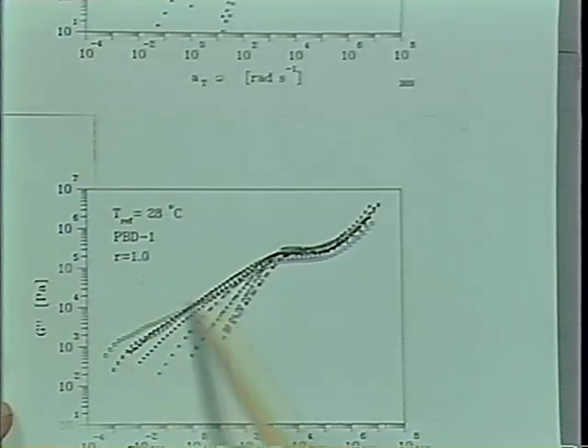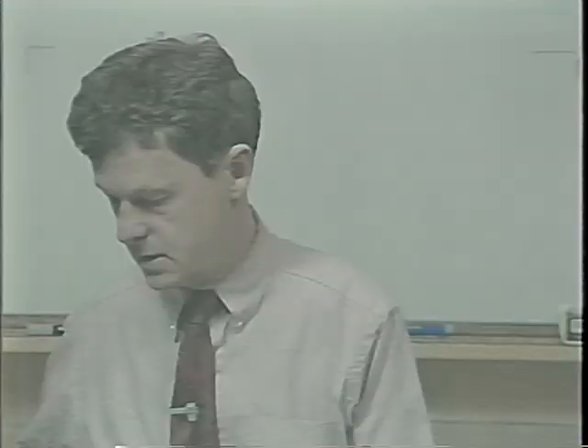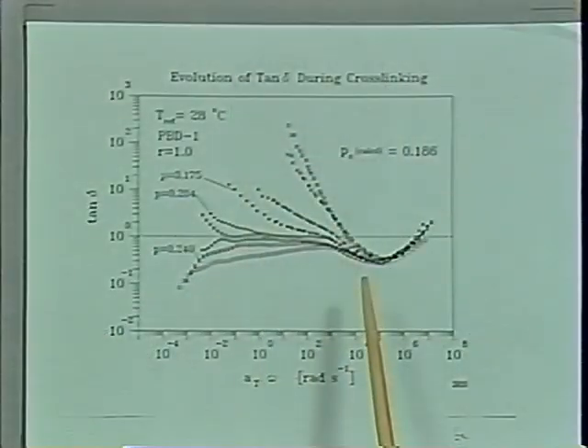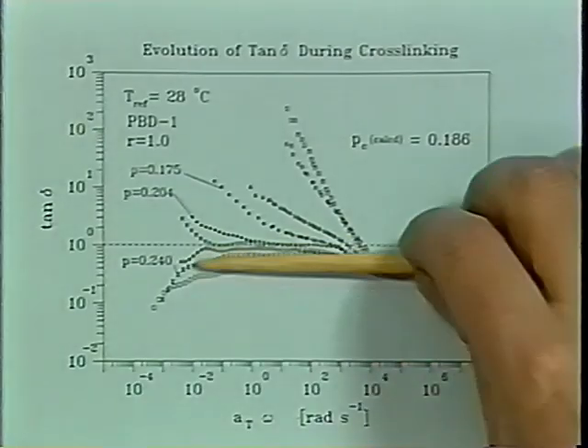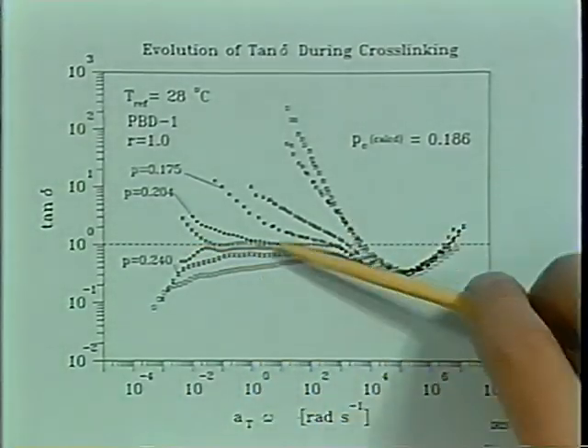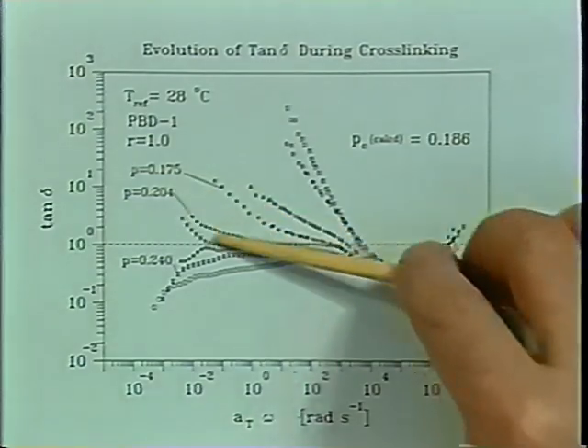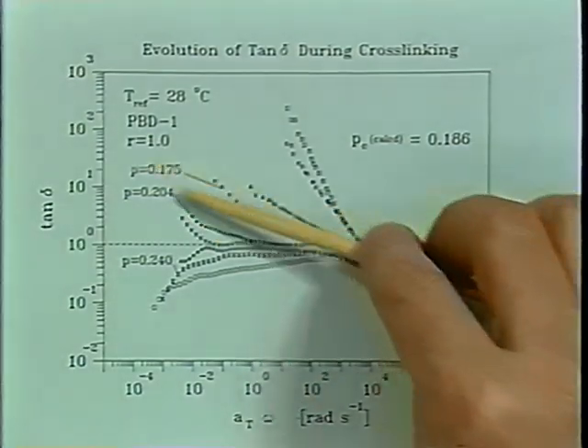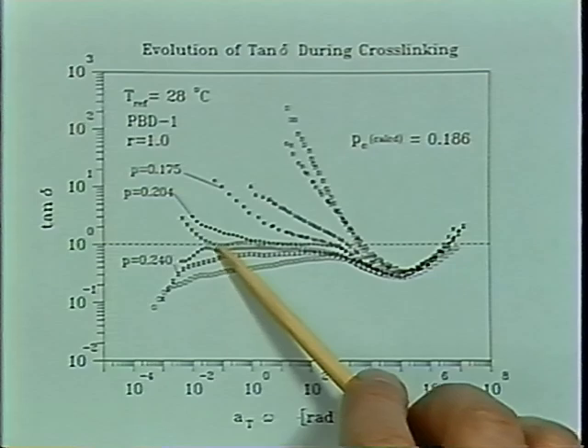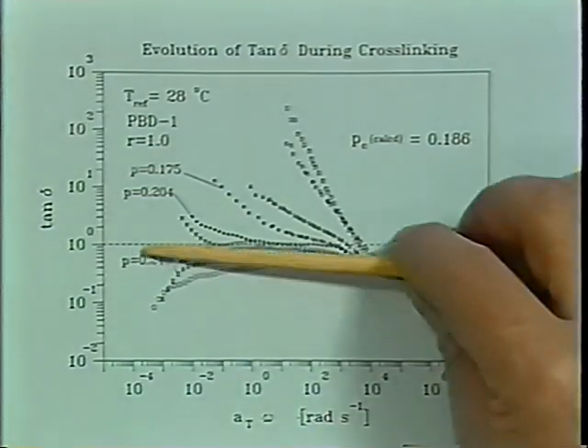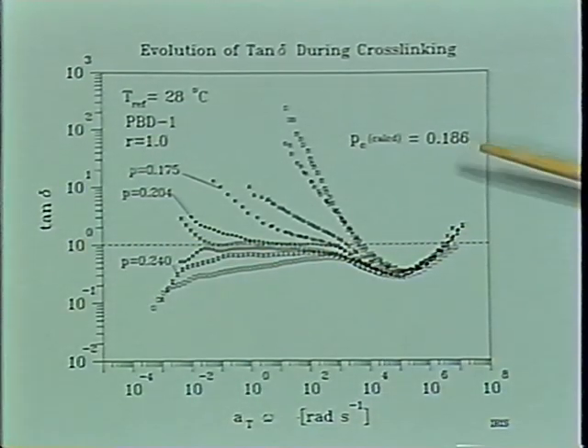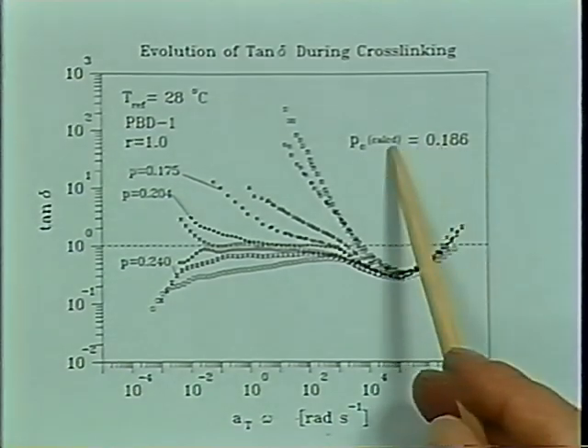Here for G double prime, it's harder to identify where the gel point is. Tan delta is even more critical for the sol-gel transition. We would expect a constant tan delta in the terminal zone. Tan delta should be flat here. And before the gel point, the material at low frequency, at long times, should act like a fluid. Tan delta will go up. And beyond the gel point, it goes down. And the gel point occurs at a conversion of about 20%. And later on, we will talk about this.